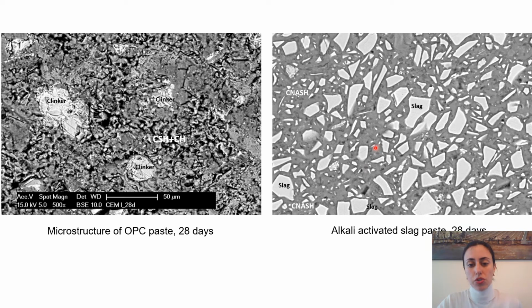Namely, the microstructure differences are very important for these two types of concrete. For alkali activated, for instance slag, the microstructure is so well developed, or let's say so dense at 28 days, while in OPC, or ordinary Portland cement paste, there are still so many porous spaces where the cement hydration is still continuing.